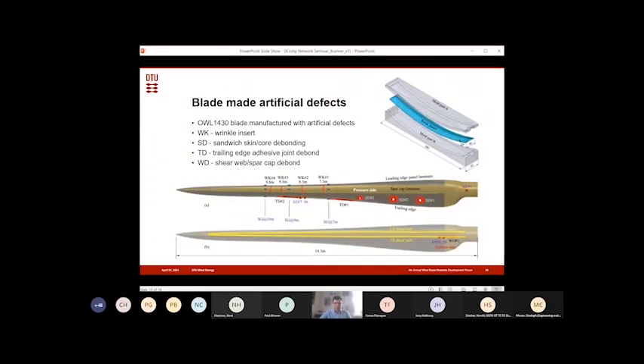So we have had the blade manufactured with a number of defects on purpose. It's a small 14.3 meter blade. There are 4 wrinkles inserted into the spar cap. There are trailing edge delaminations, and there are also some sandwich skin core debondings, and there's also a shear web spar cap debond inside the blade. So the illustration here shows how these delaminations are made by casting resin pocket inserts that are put into the blade. And then we test the blade and see what's happening.